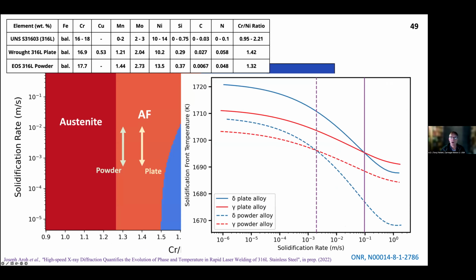And it turns out that what you have to look at is the ratio between chromium and nickel. It further turns out that stainless basically has to do with the chromium content, but most stainless steels are used as FCC materials, not the BCC. And most of these stainless steels, the composition is rather close to the break-even point. And what's even more interesting is that if you model what's going on at the dendrite tips, what you find out is that the actual local solidification temperature, which is reflective of the local driving force, varies as the solidification rate. So this is a case where it is quite sensitive to the solidification rate.